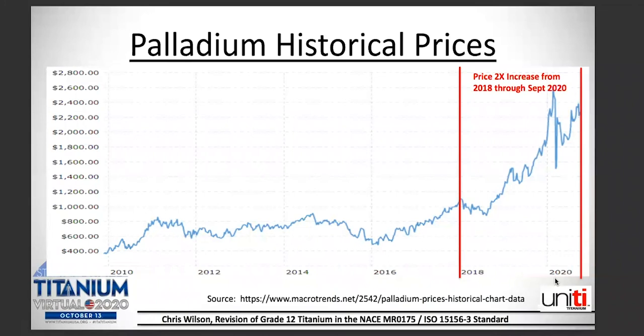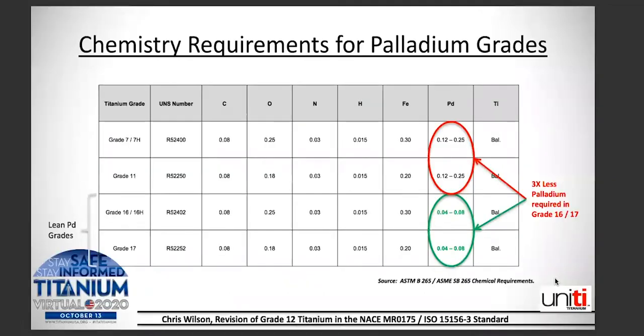But palladium's always been expensive, ranging from $800 to $1,000 for the past 10 years, but now we're up around the $2,200 range per ounce. So what are the requirements? Grade 7, the chemistry difference is between standard grade 7, grade 11, the palladium range is 0.12 to 0.25%. Now, the lean palladium grades, grade 16 and 17, the required range is 0.04 to 0.08%. So that's basically 3 times less the amount of palladium required in the lean palladium grades.